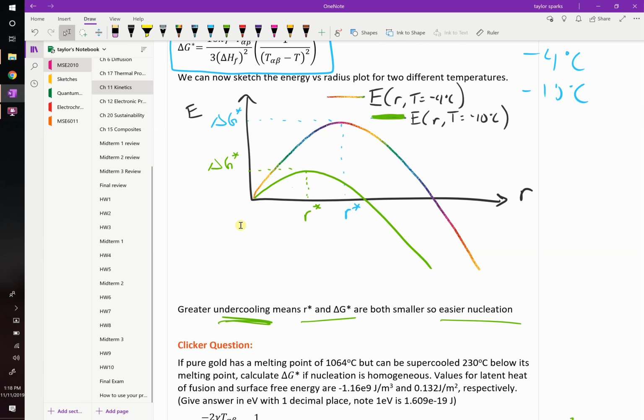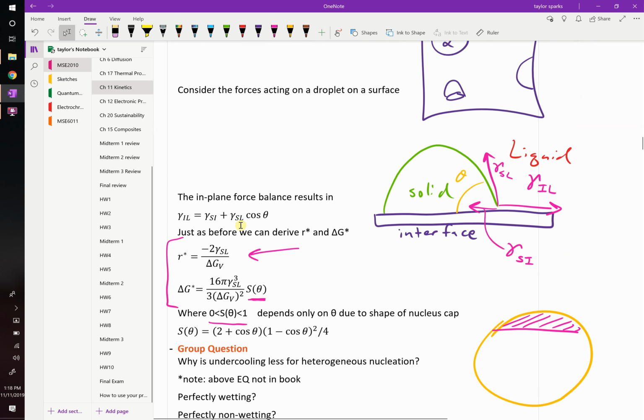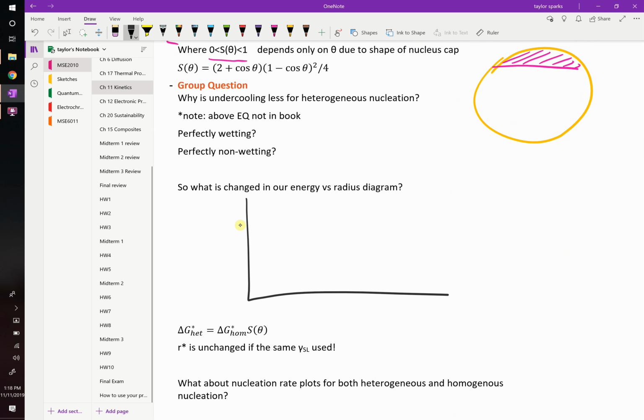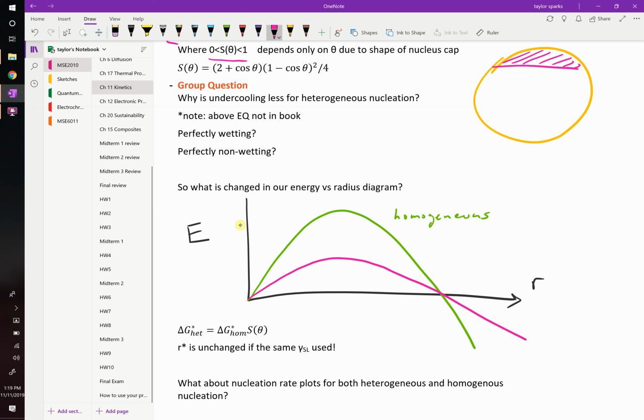So if we were going to plot that, this was our plot from before. How would we modify this plot? Let's sketch it again. Okay? If we were going to modify that, it would now look like this. Again, plotting energy versus your particle size, R. Homogeneous might look like this. So this is homogeneous. Whereas heterogeneous is going to look like this. Okay? In other words, these both have the exact same R star value. They both have to reach that same size, but one has a much lower activation energy. So we would say that this is delta G star homo, and this is delta G star hetero.